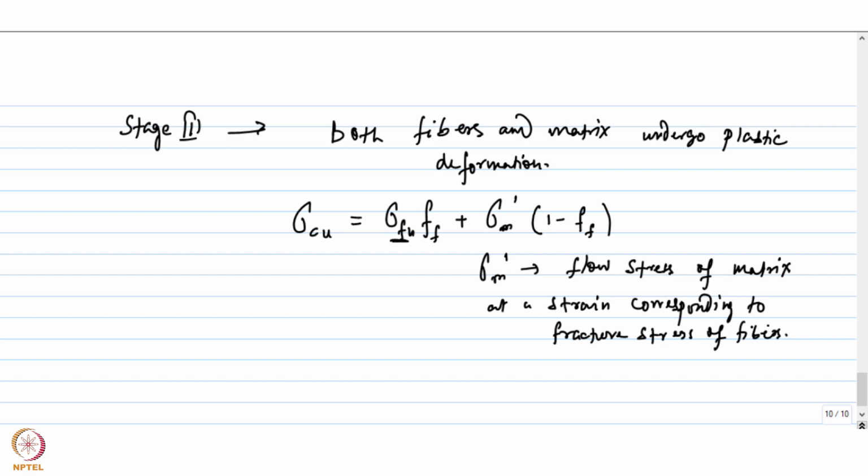So in order to obtain any benefit with regard to the strengthening that the fibers could impart, there has to be a critical volume fraction of fibers beyond which the strengthening effect can be obtained. If it is below that critical amount, then you may not get the strengthening from the fibers.